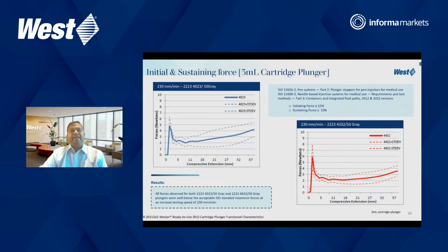Similarly, when we look at a higher speed of 230 millimeter per minute, here also what we observed is the break loose force, or the initiating force, is hovering around 4 to 5 Newton in case of bromobutyl options, and 5 to 6 in chlorobutyl 4432 options. So whether it is 80 millimeter per minute or we have increased to 230 millimeter per minute, the actual range of break loose and glide force is well within the acceptable limit in both the cases, whether it is chlorobutyl formulation or bromobutyl formulations.